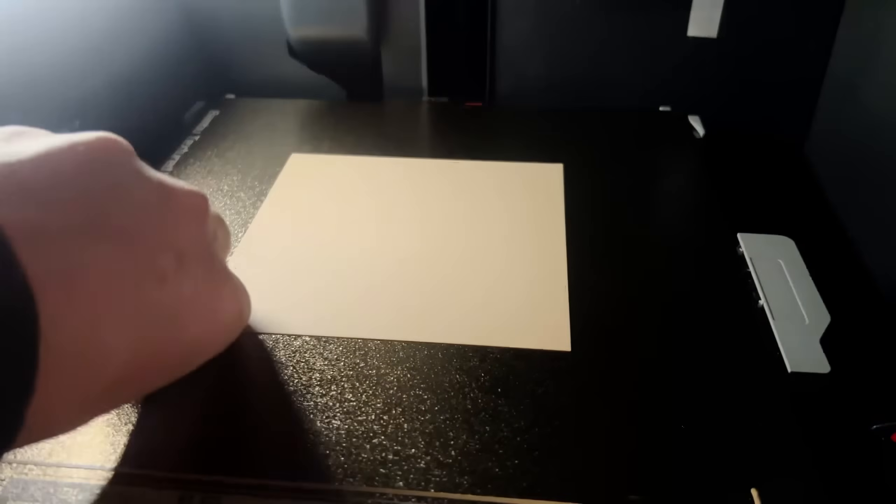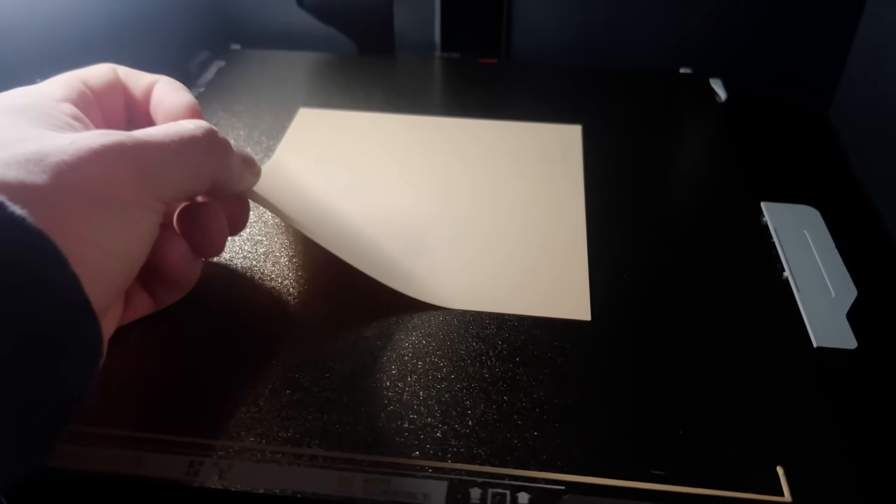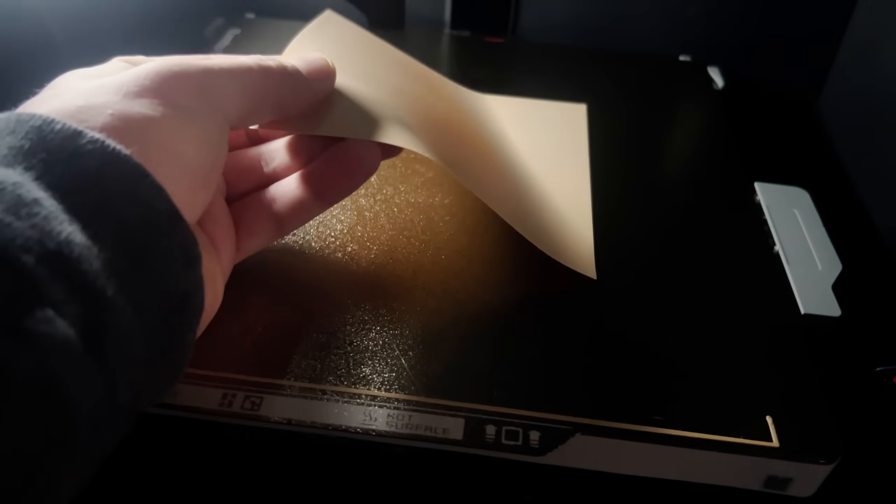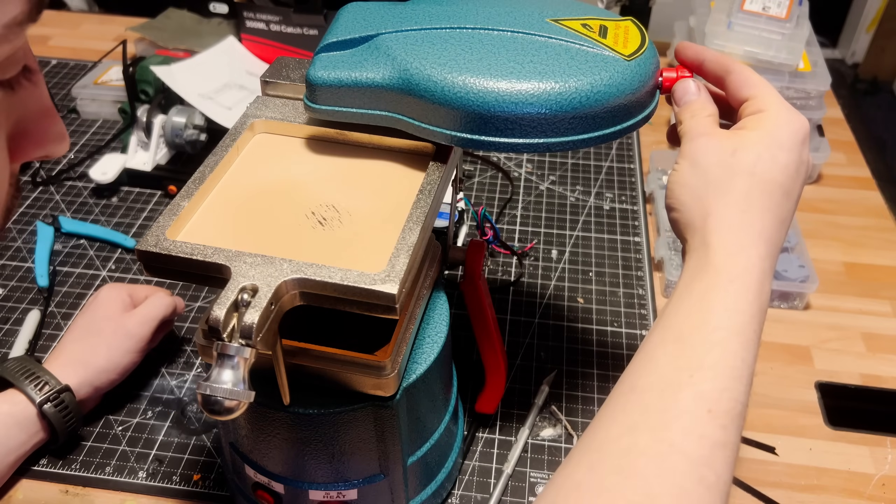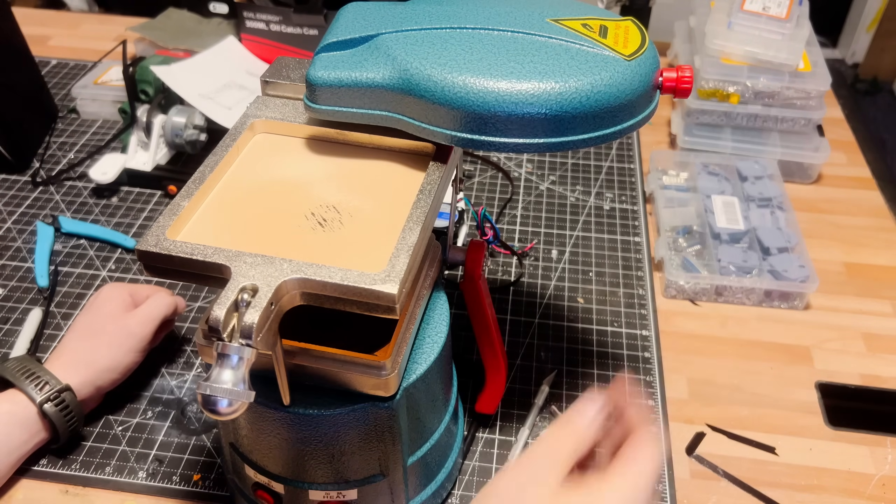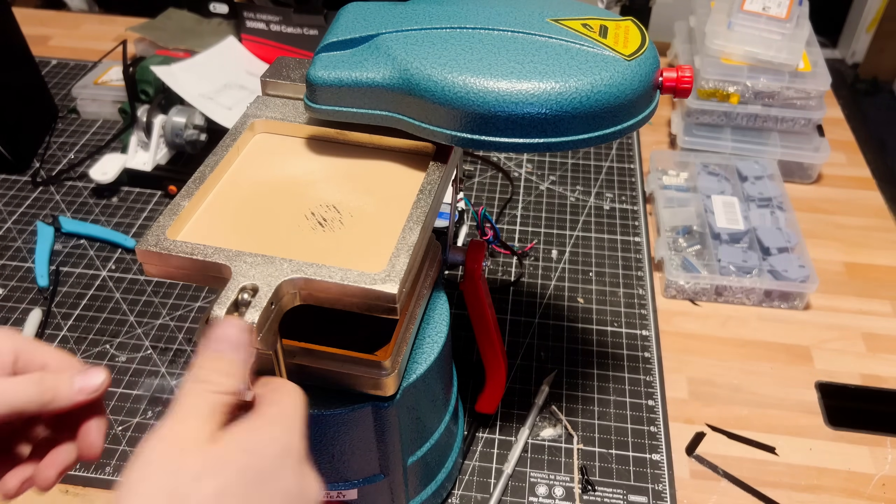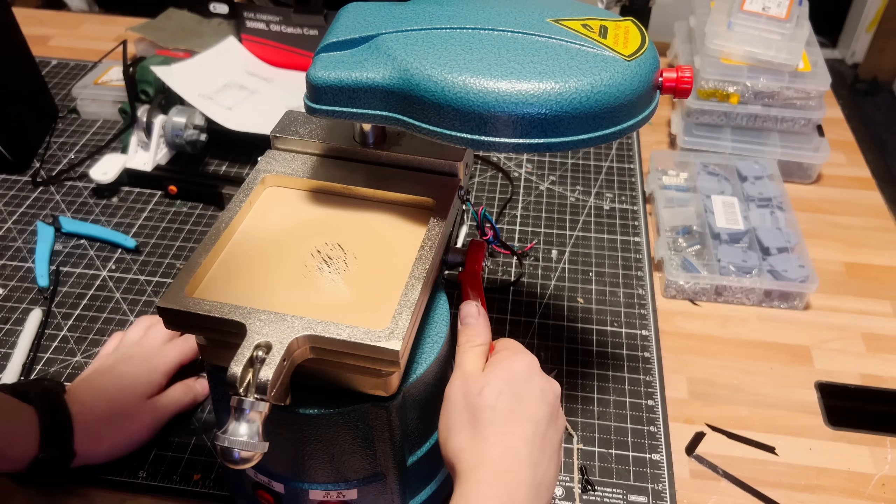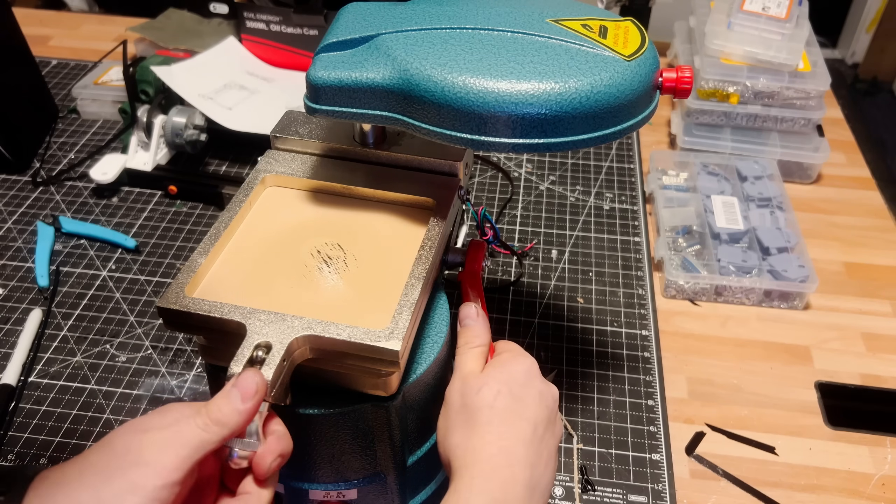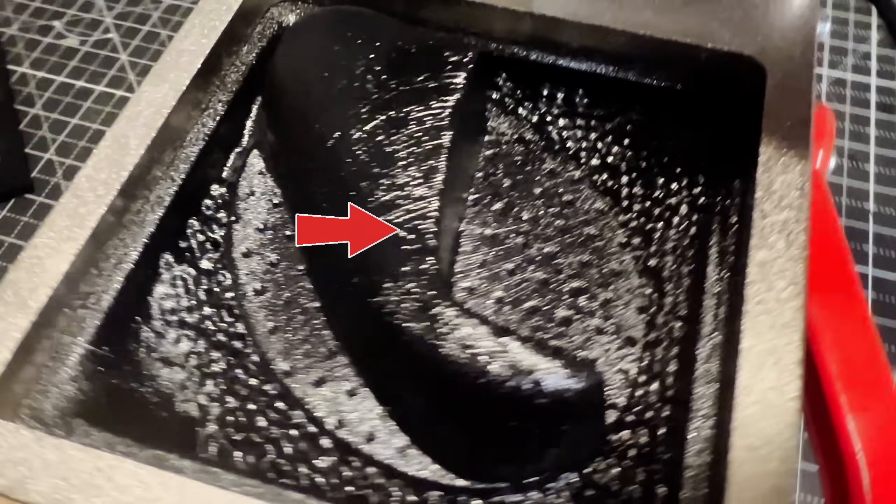The thermoplastics are thermoplastics, so better color and thickness variety is possible with printed sheets. The drawback to this is sometimes you experience separation of the print lines on each layer as it stretches over a mold. This was slightly prominent in my belt cover. I had lots of issues that I didn't document when using sheets printed at 0.2 millimeters thick for speaker cones on this as well.